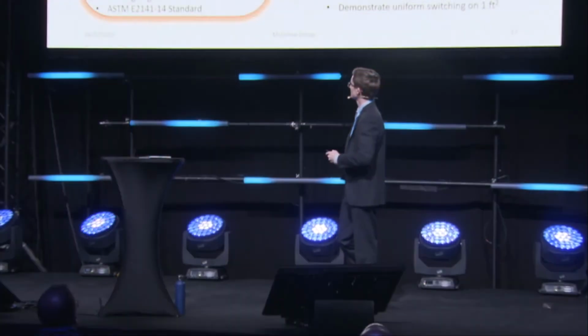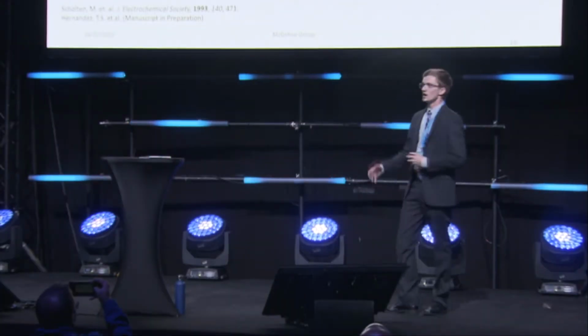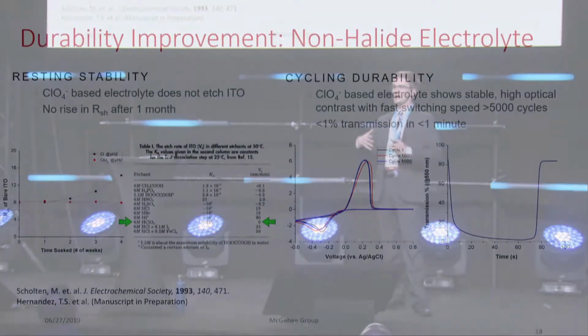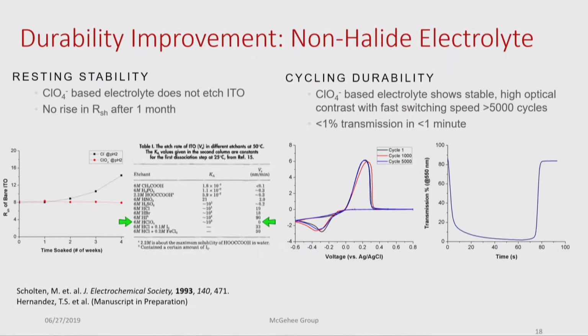So what we noticed is that the acidic halide electrolyte that contains our bismuth copper system will actually start to slowly etch away the ITO surface over the course of a month. And we were able to notice this on the far left. You can see on the far left, we would note a slow rise in sheet resistance of the ITO electrode over the course of a month. And this will eventually cause the window to switch non-uniformly and eventually stop working entirely over long periods of time.